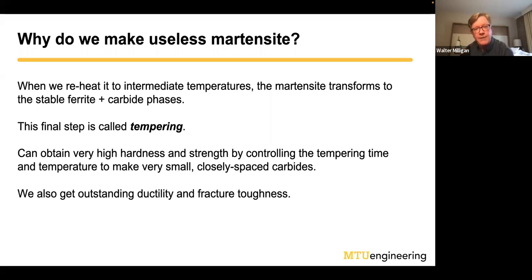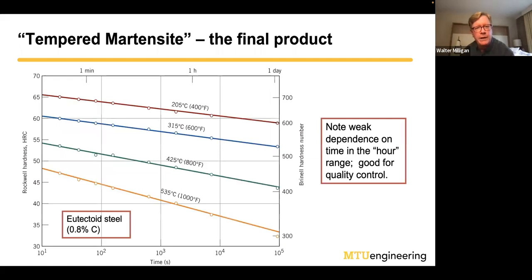And the amazing thing about these steels is they also have unbelievably high ductility and fracture toughness. And so that's one reason why these are so useful, not only in knives and things like that and in hori-horis, but also in a lot of engineering materials and components. The way you control the properties after the quenching step is by controlling the temperature and the time of the tempering. And so this plot here shows a tempering curve.